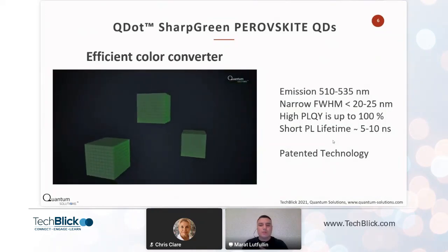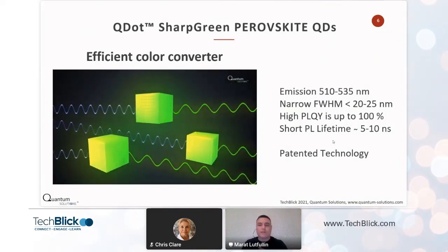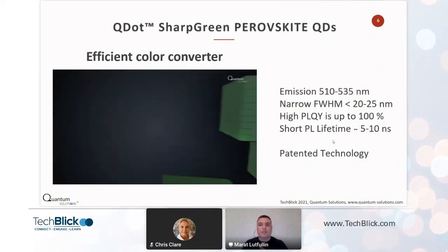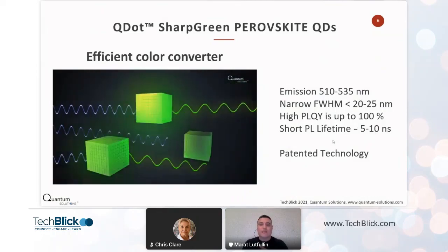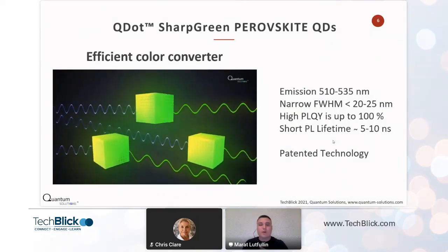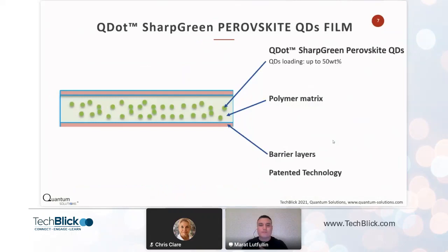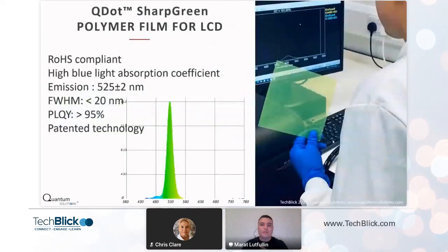The emission of our quantum dots is variable from 510 to 535 nanometers, depending on quantum dot loading and composition. It has very narrow full width at half max, high quantum yield, and very short PL lifetime. In order to use this in different devices, we developed a polymer film with sharp green quantum dots inside. Quantum dot loading might be variable with the maximum concentration up to 50wt%. And the first application where this film shows promise, of course, is displays, for LCD backlighting.